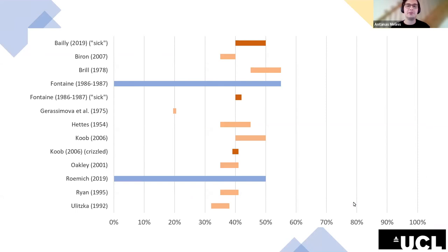And the ranges in blue signify unspecified values up to a certain RH, while the ranges in bright orange define stricter conditions for objects already undergoing active deterioration. And you can see they vary considerably and can understandably be quite broad because there's so many other factors at play. But the more defined ranges usually center on around 35 to 50% RH.